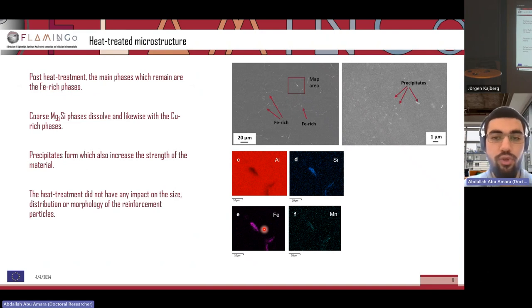So post heat treatment, once the material was heat treated, of course, we characterized the microstructure again. And as expected, the large coarser Mg2Si phases and the copper-rich phases had dissolved. What we mainly had left were these iron-rich phases. And of course, we also formed some precipitates, and these precipitates aid in the strengthening of the material.